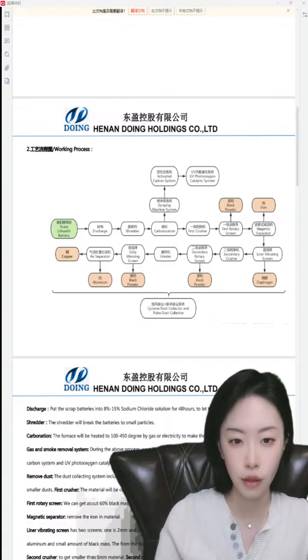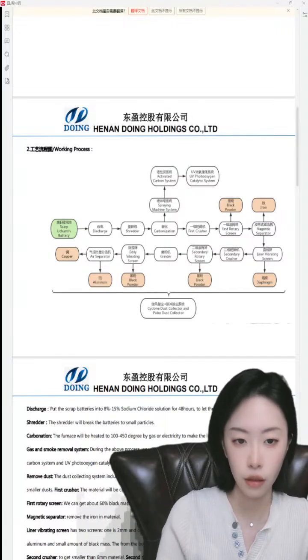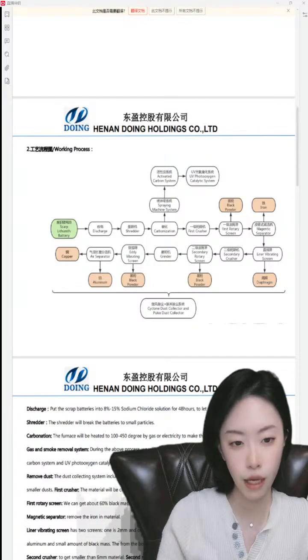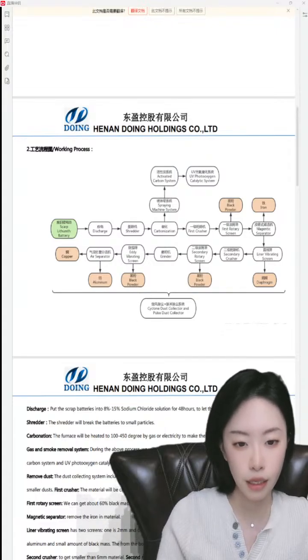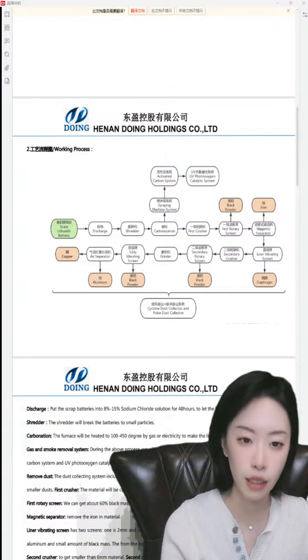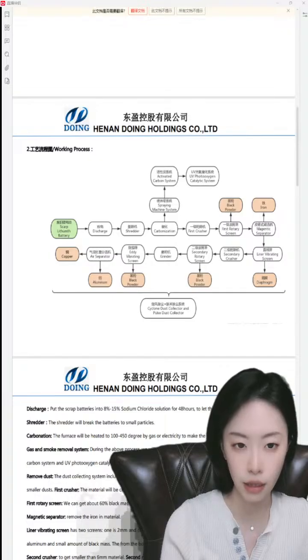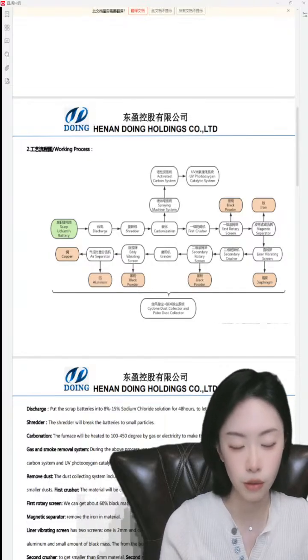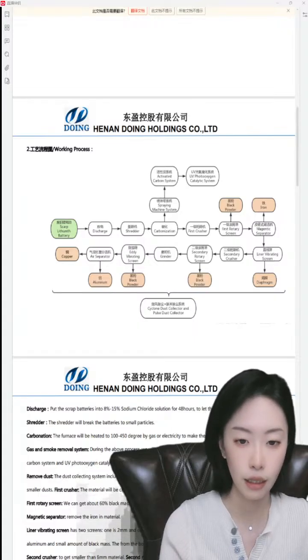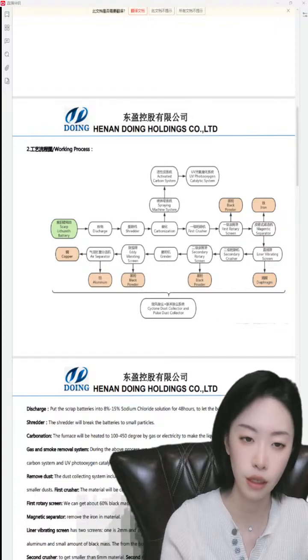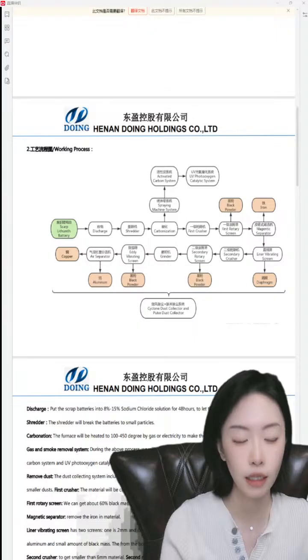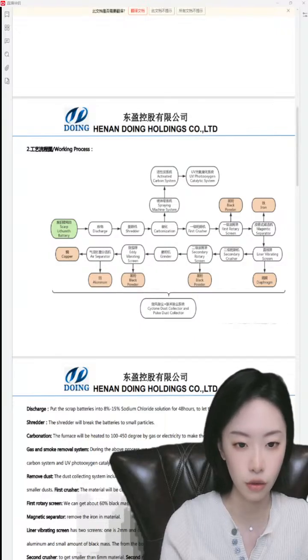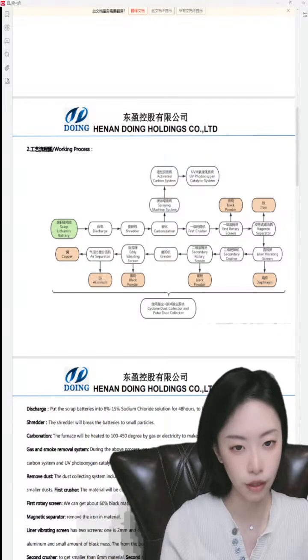Before drying, we have a pre-processing step. We will use the double shaft shredder. It will crush the materials to around 2 to 5 centimeters, and then they are put into the drying machine to evaporate the liquid. The furnace will use electricity heating or gas heating, and the heating temperature in the furnace is about 100 to 450 degrees, and the electrolyte in the battery is completely volatilized, to give the batteries a harmless treatment.